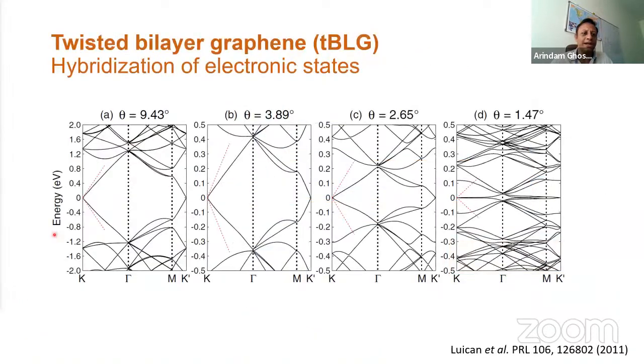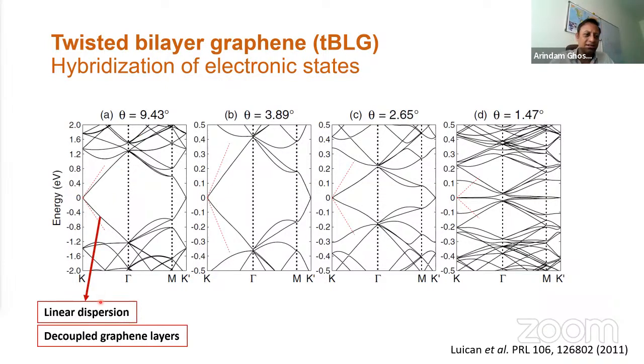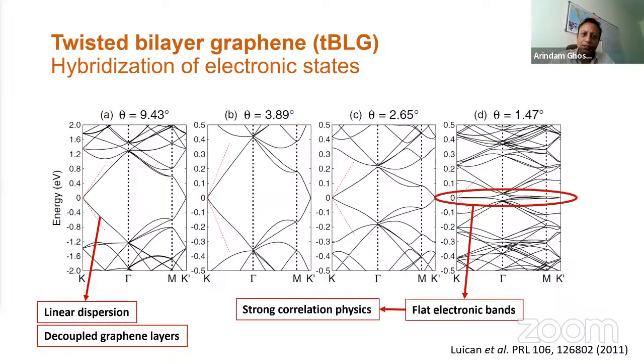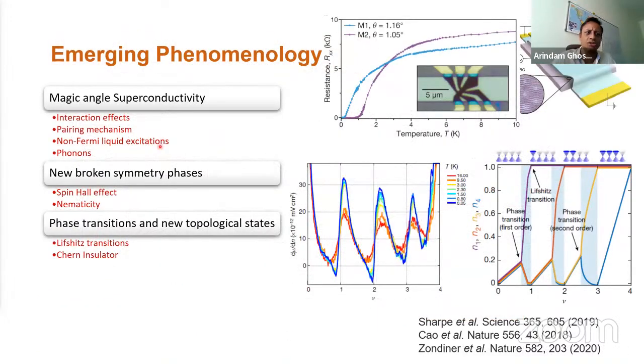So if you take 2 layers of graphene, the calculation shows that if the angle between 2 graphene layers is very large, then they essentially are decoupled. Their physics don't hybridize. The interesting thing happens when the angle between the two graphene layers is on the order of 1.4 to 4 degrees, and that leads to this flattening of the bands, and that leads to strong correlation physics.